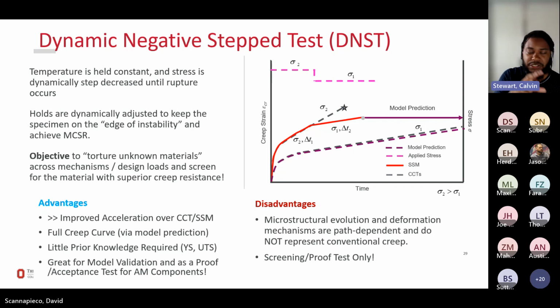And it tortures it across a number of mechanisms, different load levels that can transition through real mechanisms that can exist in that material. And from this torture test, it gives us a comparative ability between AM parts that may have different build orientations, process parameters, maybe different powder chemistry. But what's also an advantage is that this test is even faster. This test accelerates at a higher rate. But the disadvantage is that we're not really nucleating phases that we would expect because we don't know what phases might nucleate. Next slide.